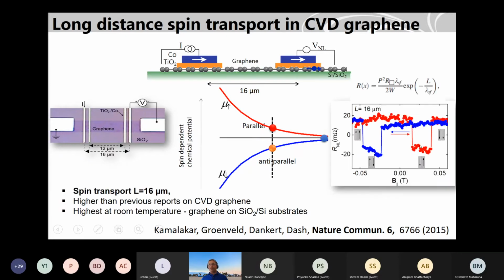So for the parallel, you have this voltage range here. This becomes a resistance: voltage divided by the supplied current. What you see is this change in the resistance, because you are measuring the spin chemical potential for the up spin and down spin in these two cases. This is what you see, the normal so-called spin valve measurement. And this is done with lengths up to 16 micrometers, actually.